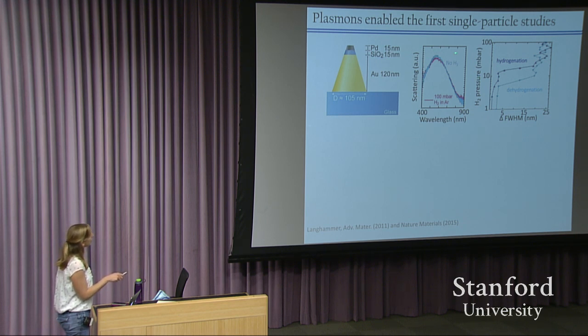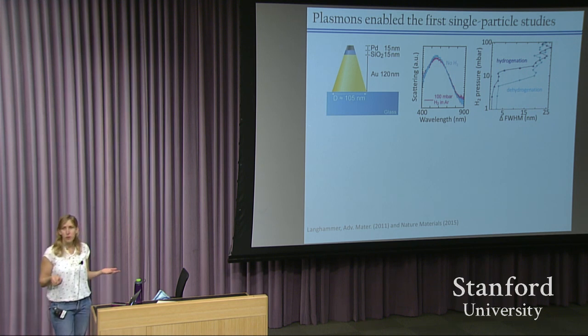And when there was no hydrogen, they got the scattering signal shown here in blue. When there was hydrogen in the environment, they got the scattering signal shown here in pink. And they were able to look at shifts. You can see in the full width at half max, there's a slight change in the line shape to map out isotherms. So the isotherms in this measurement looked quite a bit more like bulk, regardless of the size of nanoparticle they'd put on top of this gold nano antenna.